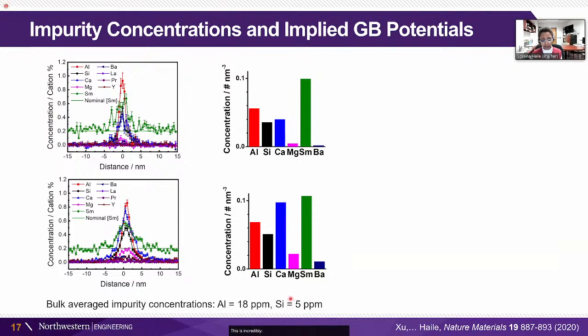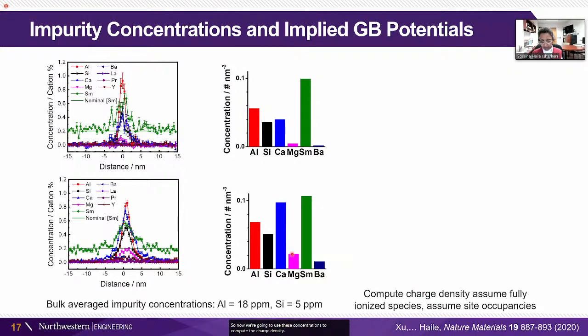This is an incredibly pure sample. So sometimes I show this and I feel like the audience says, wow, you just made an impure sample. Well, this is incredibly pure. It would be, let's say, technologically and cost prohibitive to try to make samples that are purer than this. What we're detecting are the impurities right at the interface. So even at this very low impurity concentration, we have high concentrations at the interface because these species are incredibly insoluble in the ceria.